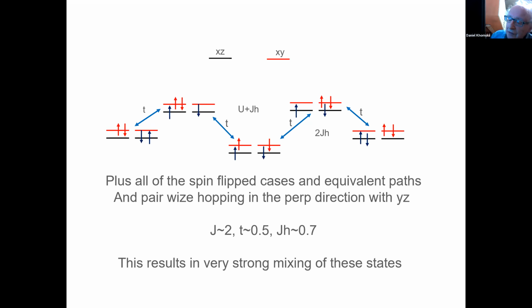If I can ask a very short experimental question, essentially. You say that superconductivity itself in iron selenide on STO is due to electron doping. But for that, you really need this STO, which is already either oxygen depleted or with niobium and so on. So experimentally, does it really depend on the quality of STO? Because if you have very stoichiometric, very good STO, then you wouldn't get any superconductivity at all. Is it really